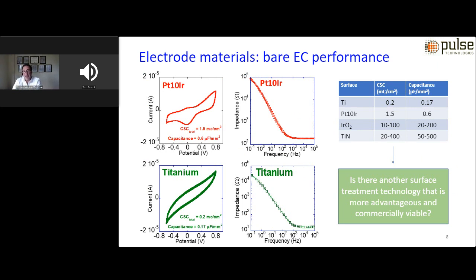So let's look at platinum iridium, as we talked about, and titanium as a starter. These two metals, without any surface treatment or coating or any addition to the surface, are generally poor materials electrochemically. Platinum iridium is electrochemically more active and better than titanium. From the CV and EIS plots that I'm showing here, you can see that platinum iridium charge storage capacity total is around 1.5 millicoulombs per centimeter squared, and its specific capacitance is around 0.6. And those same parameters or performance metrics for titanium are around 0.2 and 0.17 on average, and that's why titanium is much poorer compared to platinum iridium.